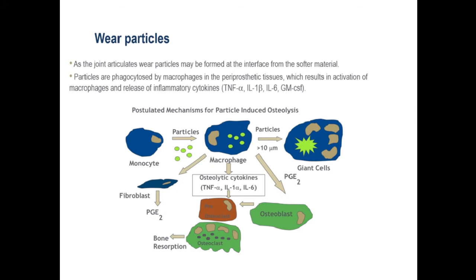Now I'm going to talk about wear debris. As the joint articulates, particles are formed at the interface from the softer material, and the particles are phagocytosed by macrophages in the periprosthetic tissues, which results in activation of the macrophages and release of inflammatory cytokines. And this is a cartoon drawing of some of the mechanisms that particles of different sizes go through in the macrophages and the release of cytokines leading to bone resorption.